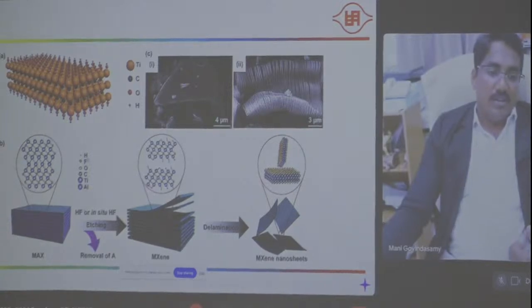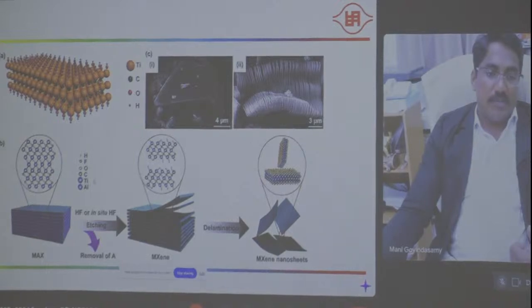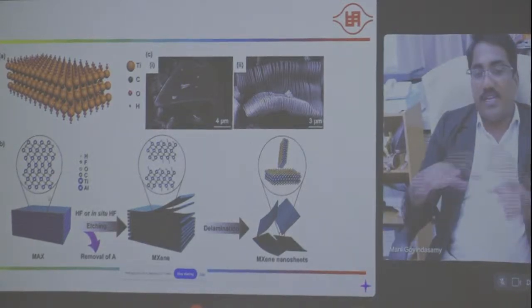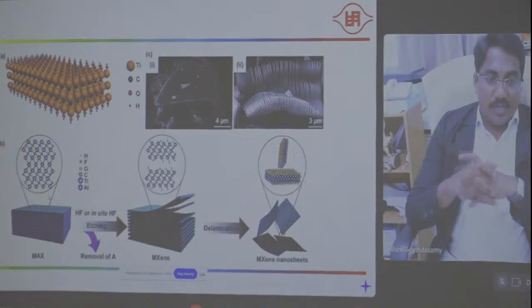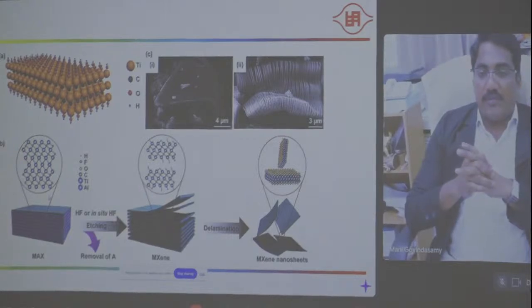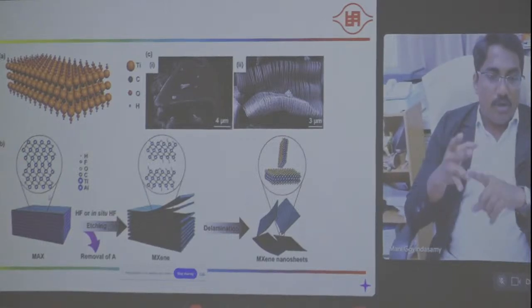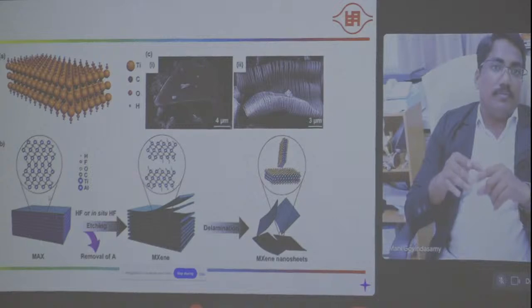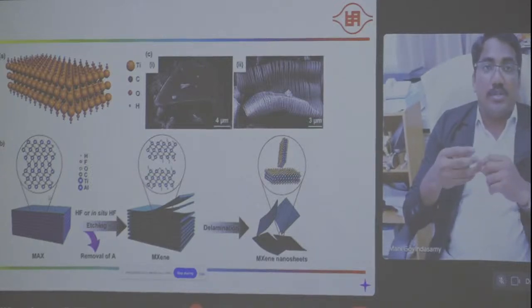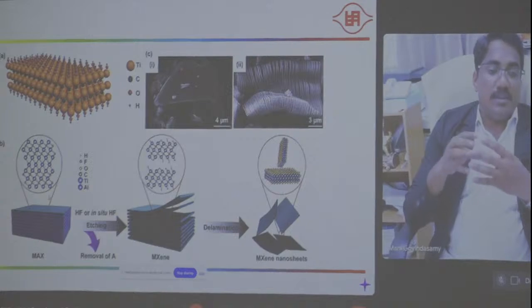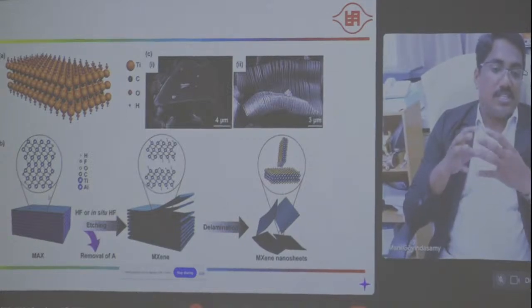For example, these kinds of elements we can exchange, for example titanium. So titanium based MXene is a very common MXene material. Apart from titanium, we can exchange for molybdenum, copper, nickel, manganese, vanadium, niobium. These kinds of elements will be exchanged in the MXene.